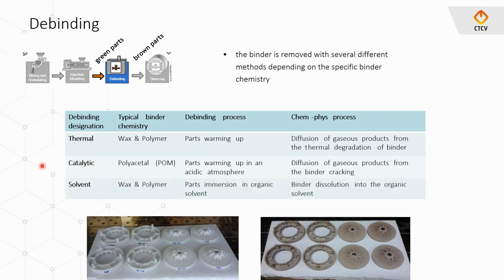And there are several other methods. Solvent method, when we have a wax and a polymer again, but the wax is soluble in organic solvent. So we put the parts immersed in organic solvent and wait for the dissolution of the wax part. And when the soluble component is soluble in water, we can use the water immersion method, which is a more eco-friendly, more environmentally friendly process.